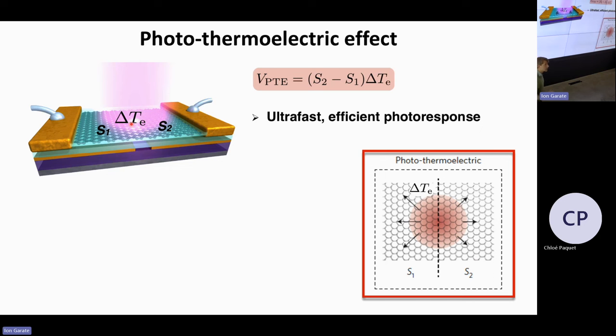And this is created on a time scale of femtoseconds, because this cascade that I was showing of electrons, that's electron-electron interaction taking place at tens of femtoseconds time scale. And immediately after that, you have this hot electron temperature. And immediately after that, you have this local photovoltage generation at this junction. So you can do this in tens of femtoseconds. So it's a very, very fast process. And it's also very efficient, because all this light that is absorbed is turned into electronic energy of the graphene system.